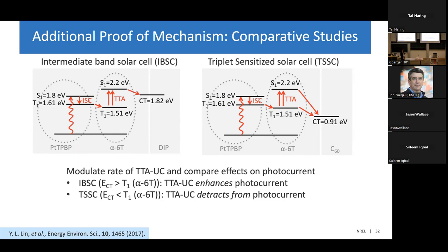So the way we modulated triplet-triplet annihilation in these devices was by applying a background light to the system. Remember I said that TTA is a bimolecular process, so it depends on the density of excitons that are present. So when we apply this background light, we expect to increase the rate of triplet-triplet annihilation.